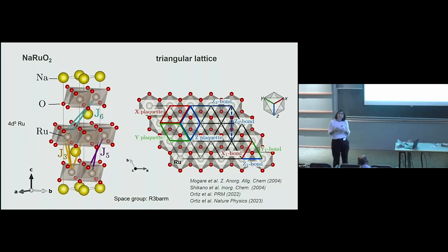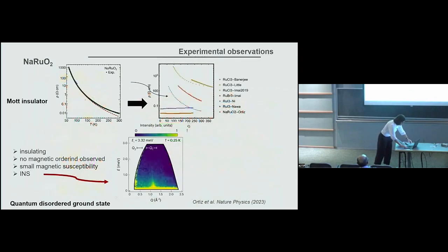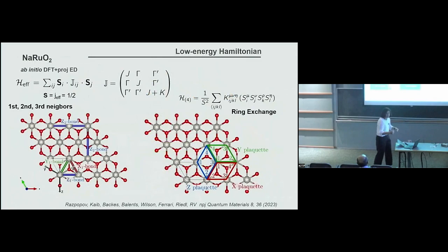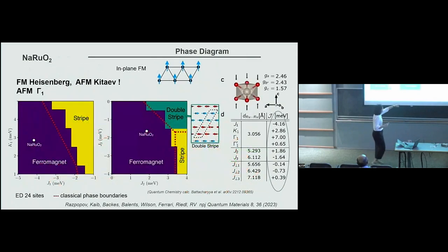But if that's the case, you have to get quite a large J compared with other ruthenium oxides. Did you see that kind of signature in your calculation? Well, in our calculations, I don't have that here, but you see, it's a combination. It's not only that there is a large J. You see these other contributions. There is a very strong gamma term, and the Kitaev term is also not small. So you have to combine all these terms into the Curie-Weiss.